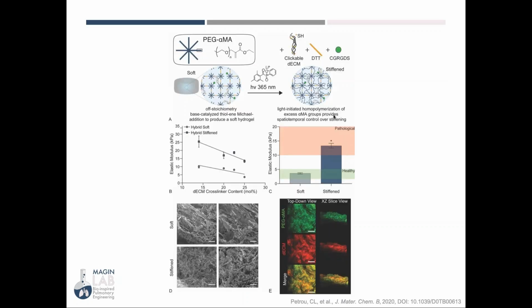Recently in our lab, a master's student, Cassandra, just published this paper. It's in the Journal of Materials Chemistry B. And what we've done is used a PEG alpha methacrylate. So this PEG material, the methacrylate is attached sort of on the opposite side as you would usually. And when this ester bond cleaves, an alcohol is released, but the PEG backbone stays intact. So we've created a PEG methacrylate hydrogel that has higher hydrolytic stability. And then we've cross-linked this with a thiolated decellularized extracellular matrix material.